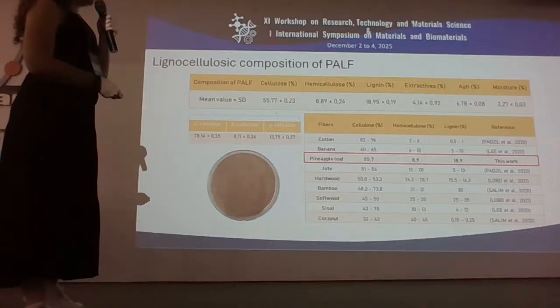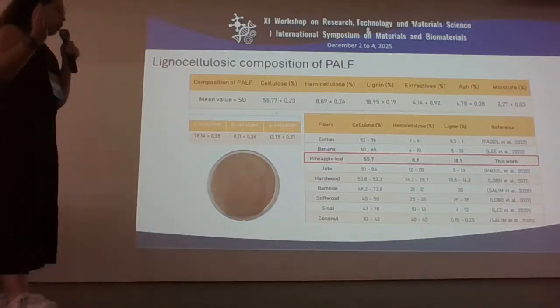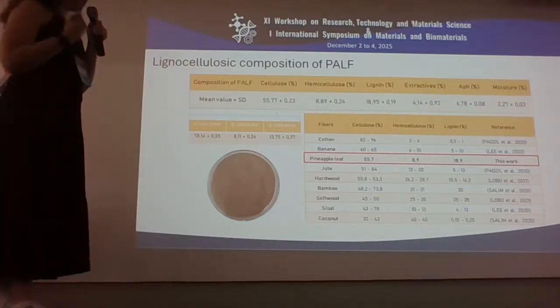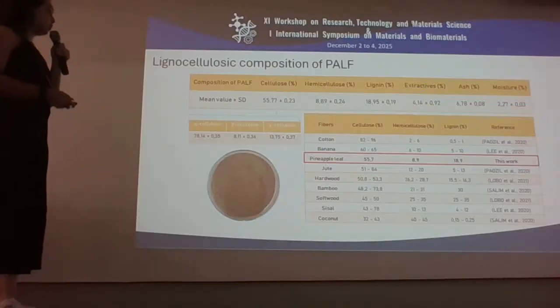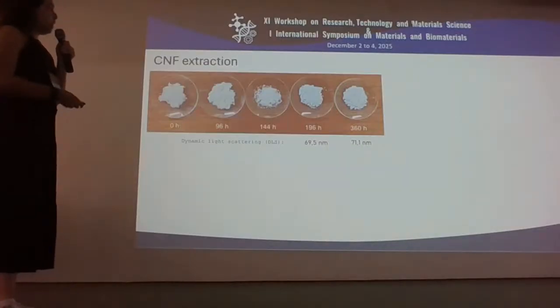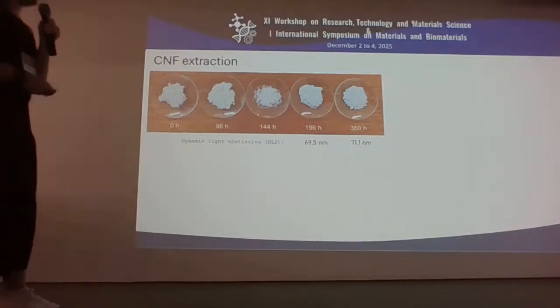It's even higher than hardwood and softwood as the most used sources to extract the cellulose. So this is a good result for this kind of source. And for the CNF extraction, we varied the time of the ball mill, and with more time we have smaller particles. It cannot just be called CNF or just CNP, the cellulose nanoparticles, because it's too small.